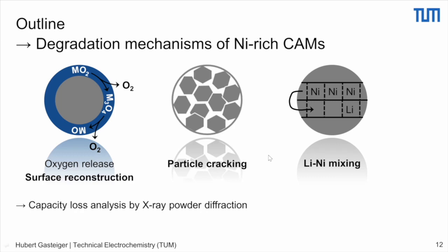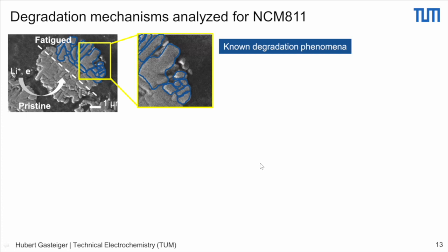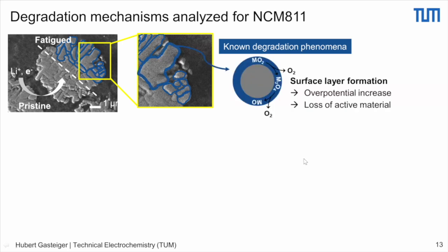powder diffraction. And when we do this, we first have to ask the question, what are the different mechanisms? We already talked a little bit about it, but essentially this is a cross-section of an NCM polycrystalline material. And for a cycled material, what you can see is cracks around all these primary crystallites. And so what we expect is that wherever electrolyte has access, we will form a reconstructed oxygen-depleted surface layer on the NCM active material. And that should lead to two things: an increase in overpotential, plus also a loss of active material if the surface layer is inactive for lithium intercalation and deintercalation.